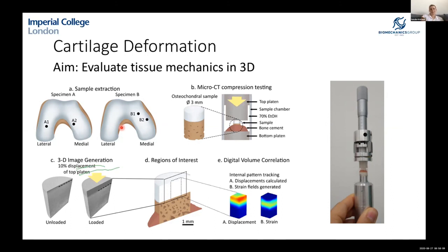Regarding physiological forces on cartilage compared to the compression applied during imaging: it's very difficult to measure in vivo forces directly, but it's easier to look at strain — the deformation applied. Typically you'd expect cartilage to cope with up to around 20% strain, which is similar to the levels we applied both for the cartilage samples and for the hybrid implants being designed. So that's a readily known strain level used as a guide.